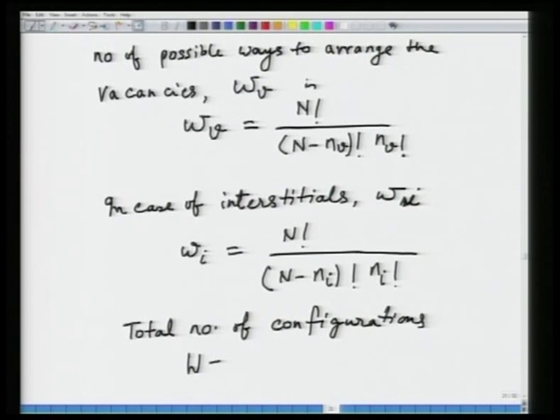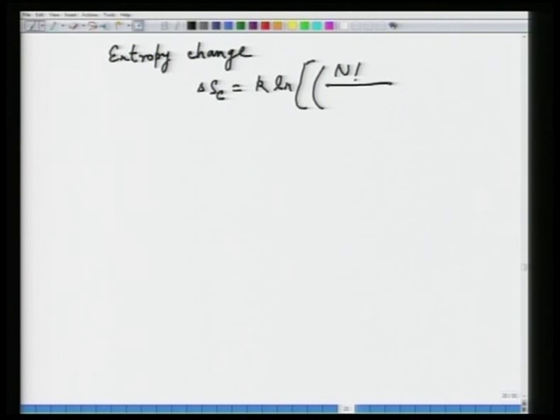We defined that as W, and this is nothing but the product of W_I and W_V. So as a result, we can work out what the entropy change is. The entropy change, delta S_C, is equal to k ln of N factorial divided by (N minus n_I) factorial into n_I factorial, and again N factorial divided by (N minus n_V) factorial into n_V factorial.